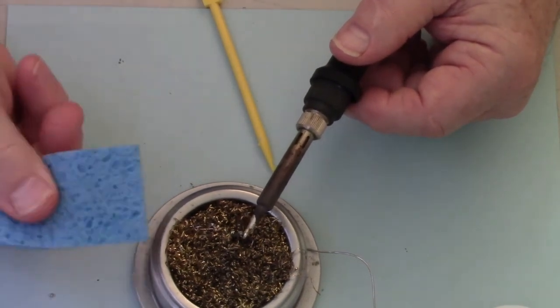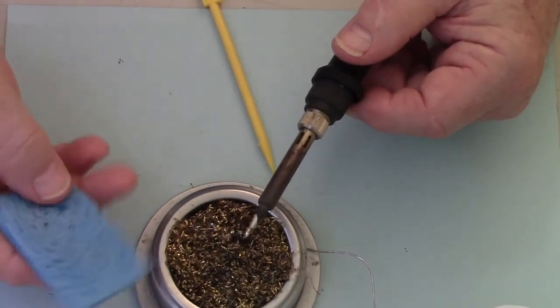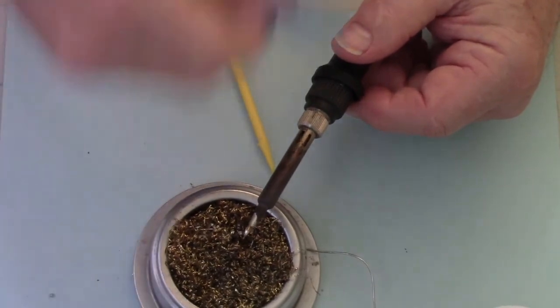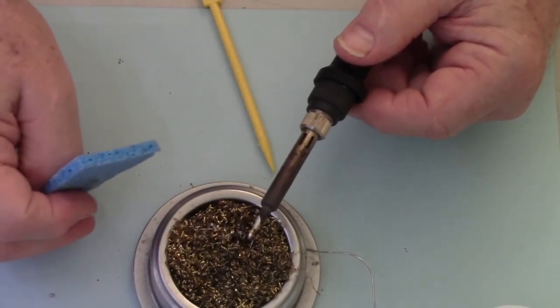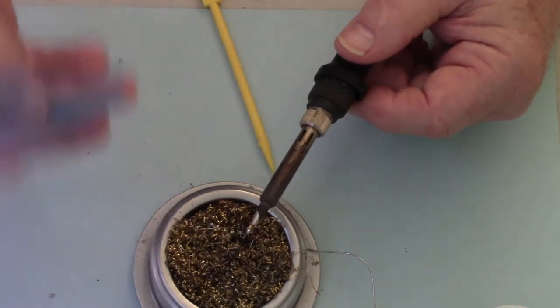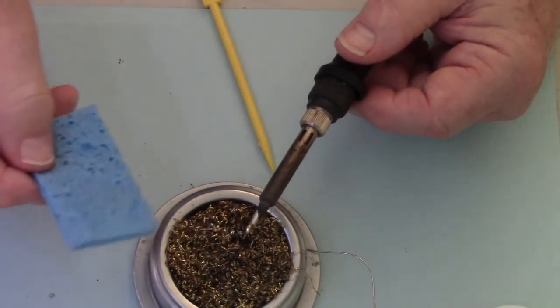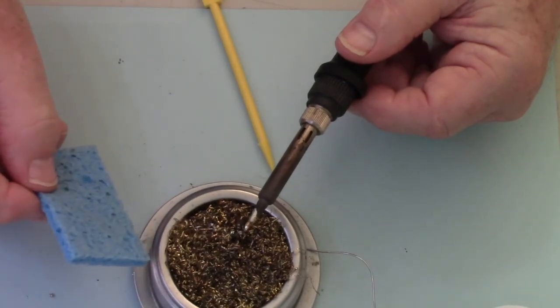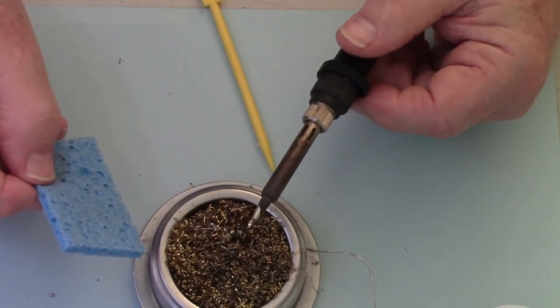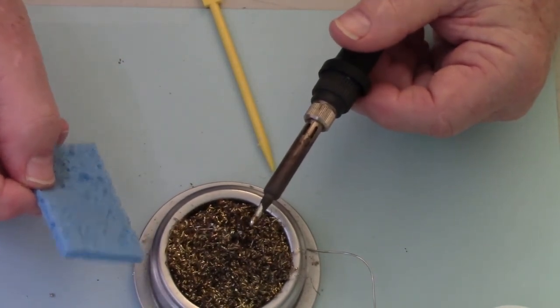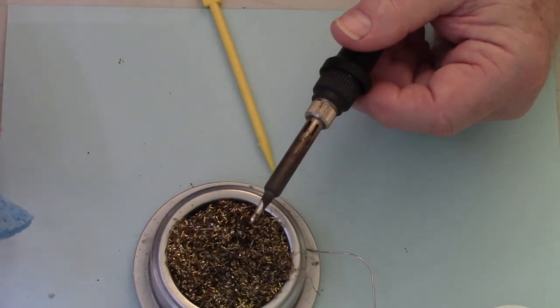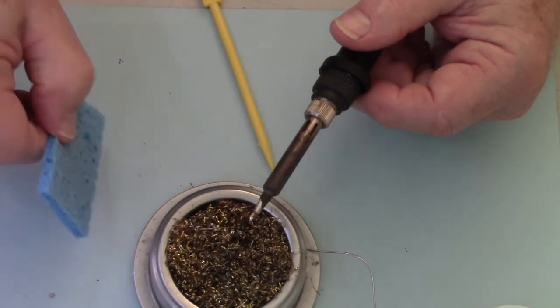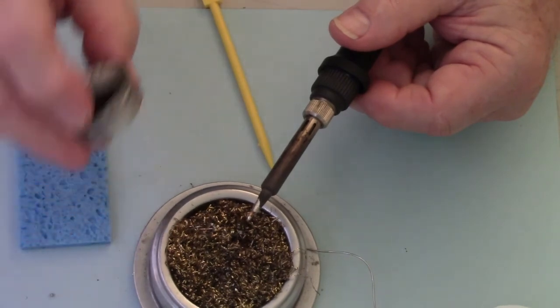The reason that I don't use the wet sponge is that every time that you're wiping it, you're cooling that tip and you're causing the iron to heat it and then cool it and then heat it, and it'll cause early breakdown of that iron coating that's on the tip. So be sparing with the sponge, be sparing with this